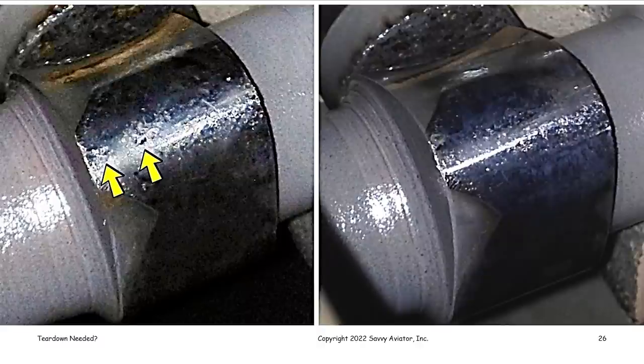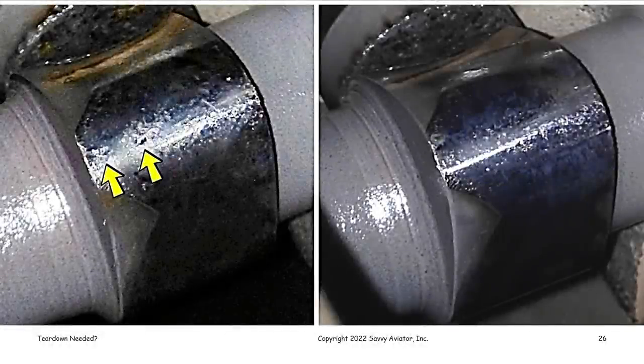So the left picture has crack-like features on the toe, and as I mentioned, that hardened layer is also fairly brittle, so it is capable of developing cracks, and that's what happened to this left cam lobe. So that cam lobe is pretty much toast, and those crack-like features not only will lead to the destruction of that lobe, but will also tear up the lifter really badly every time it comes by. It's like a chisel. But the right-hand lifter is acceptable. It's worn. It's got a little minor pitting on it, but it's okay.